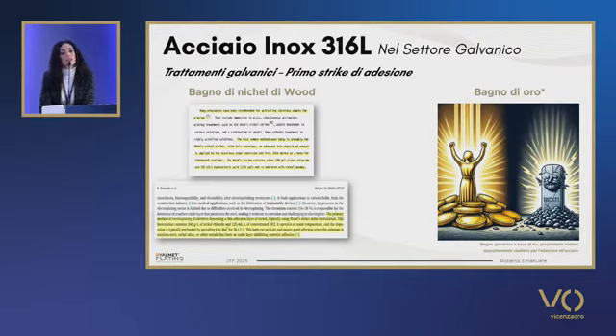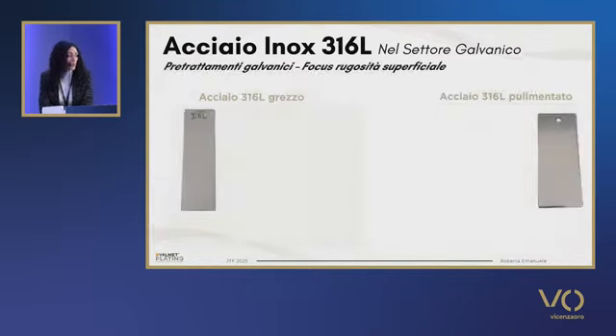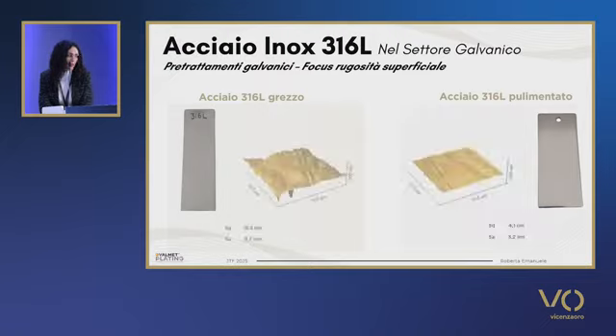These two baths were compared to analyze the nickel release, and they enabled us to understand what were the decisive factors and to see to what extent the coating, the galvanic process, as well as the surface treatment may have an impact on nickel release, as, for example, superficial roughness. The first part of this research has analyzed the roughness.